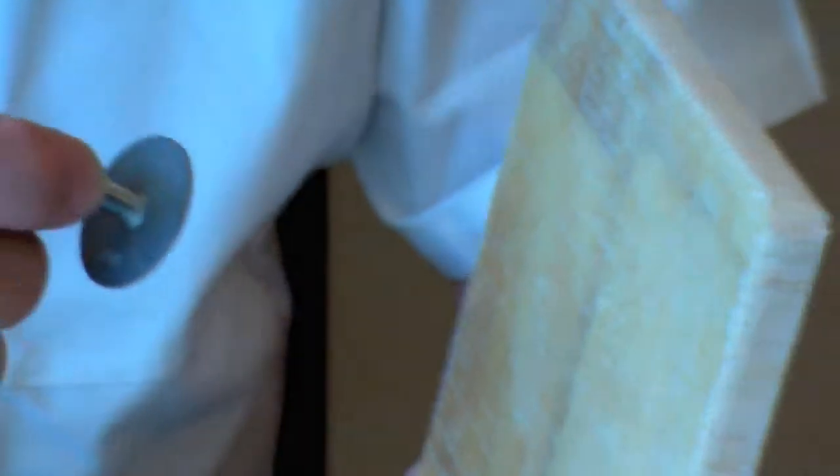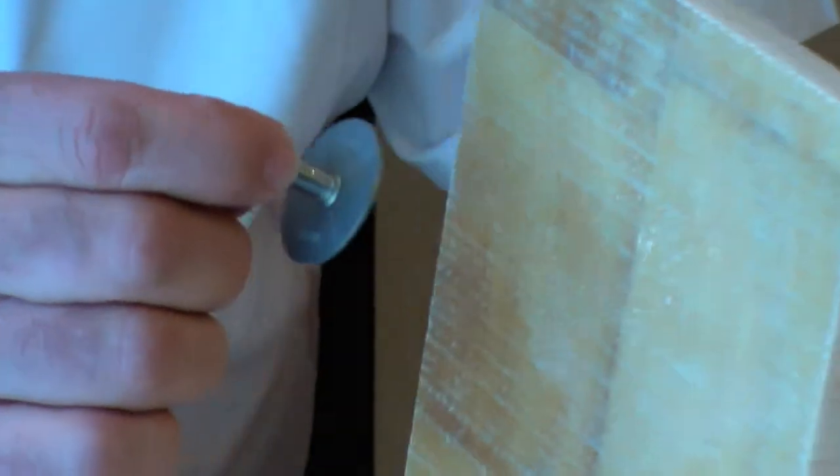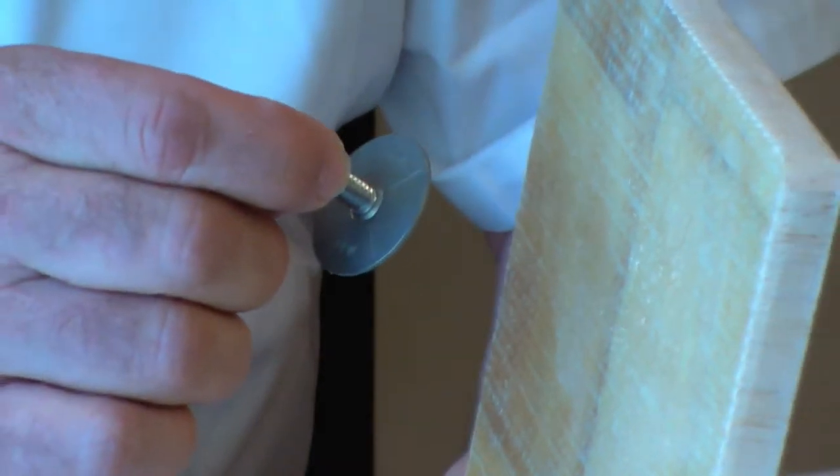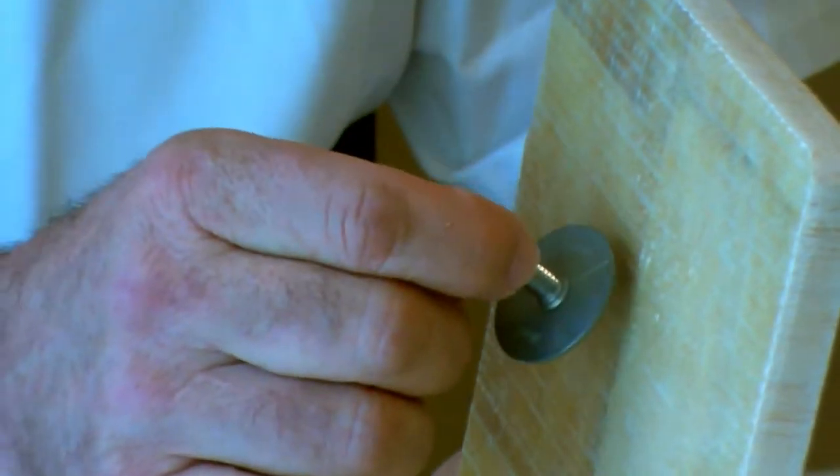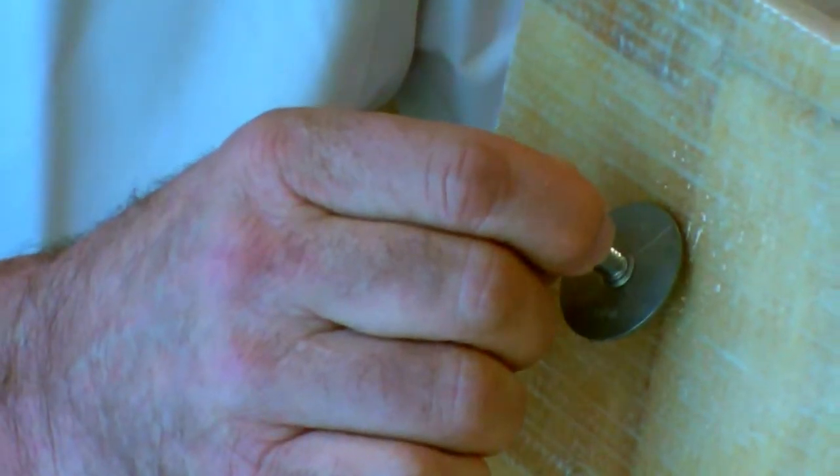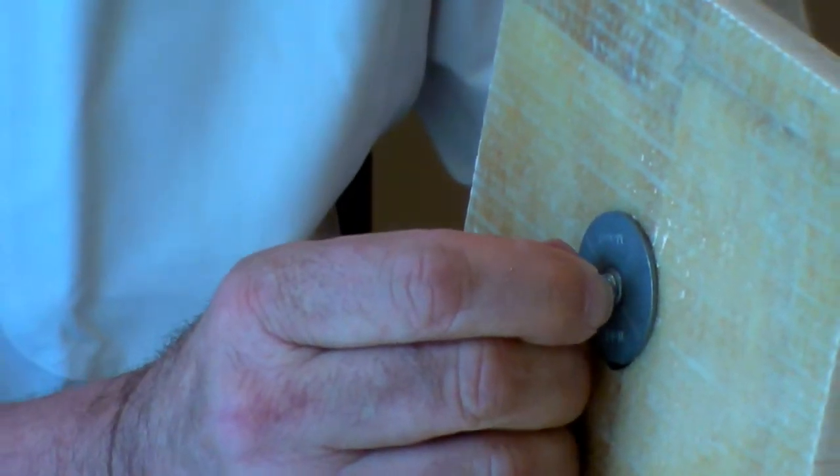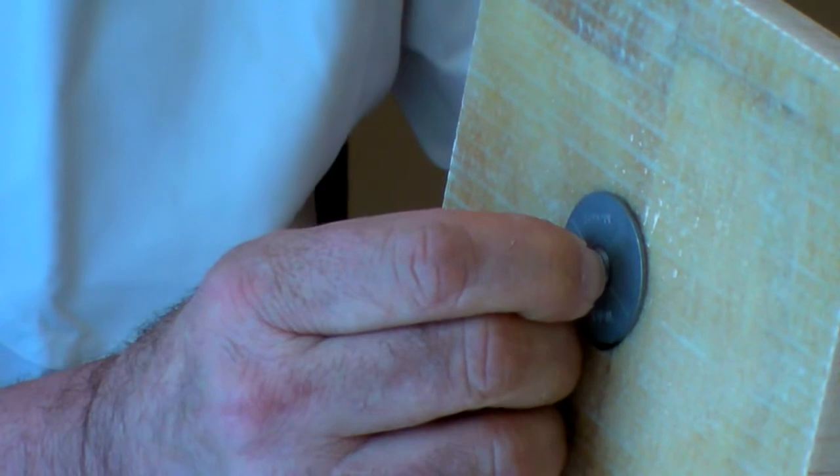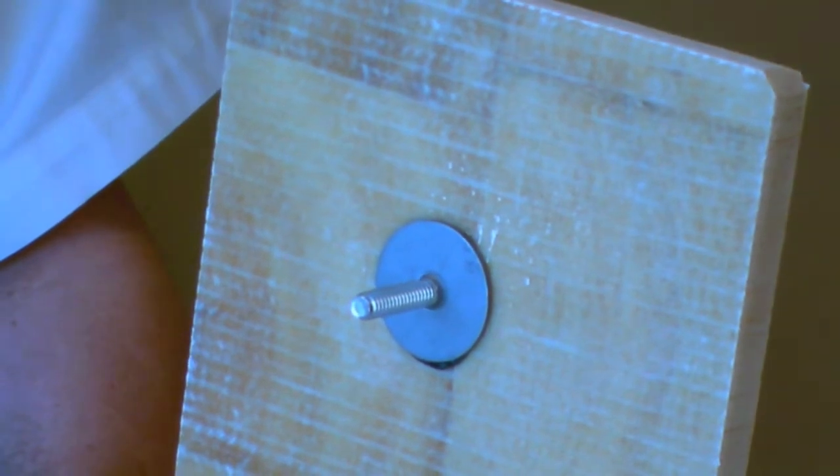It's important that you make sure that you bring the part in at a 45 degree angle so that the glue dot makes contact with the surface before the glue spreads out. Otherwise, the dot won't hold. But basically, bed it with the dot and then bring it down and make contact. Push in slightly with a little bit of rotation until you squeeze the glue out all the way around the part and let it go. And that glue dot holds the part in place until the adhesive kicks.